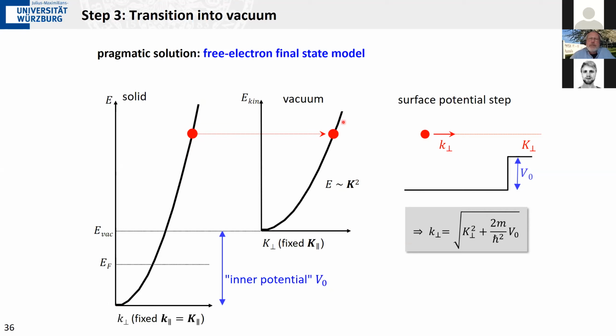And now I have a parabola here, I have a parabola there. The zero here is offset by just this inner potential, and then I have a clear analytic relationship between capital K perp and small k perp. And this is what I measure. V naught, that's the bottom of the band here. I would know roughly from band calculations, and from that I can calculate my small k perp. There are more refined solutions to this problem, how to get this small k perp, but this is a pragmatic one that very often works very well.